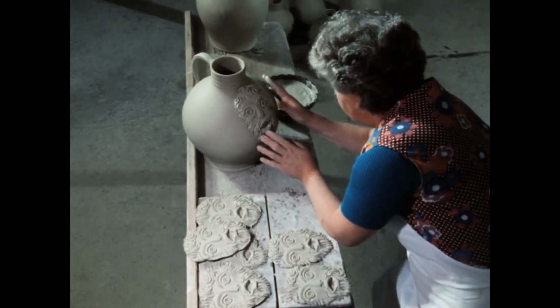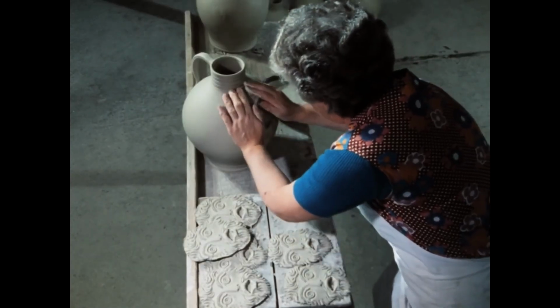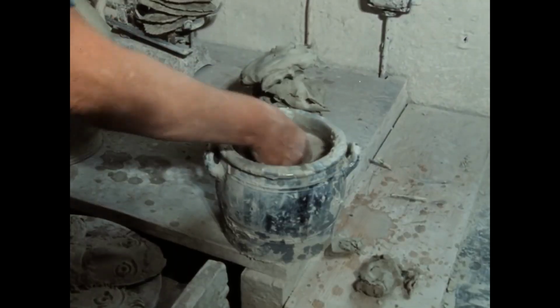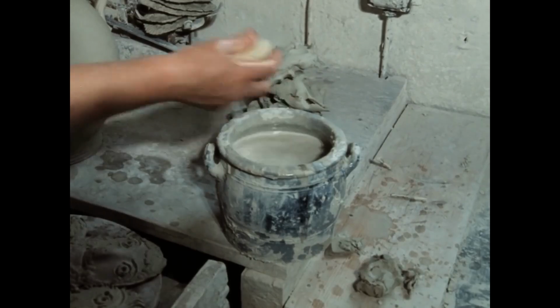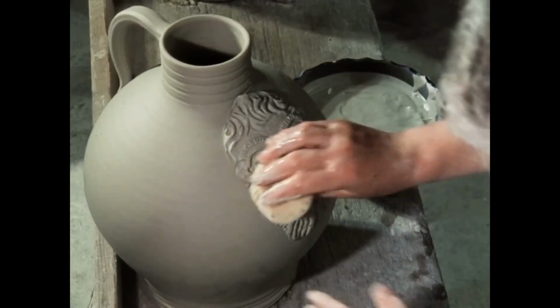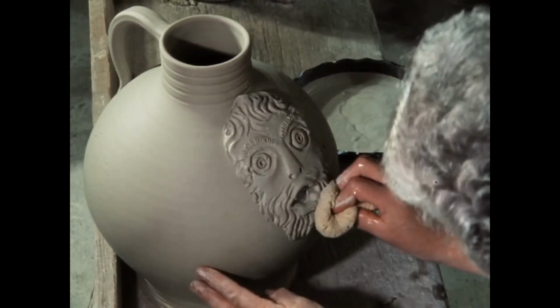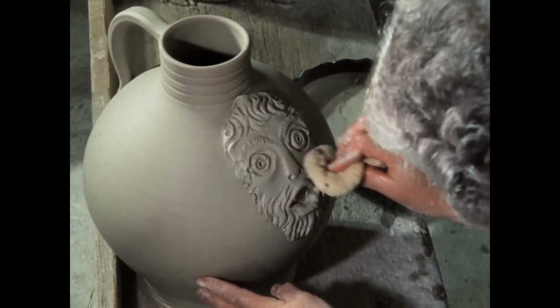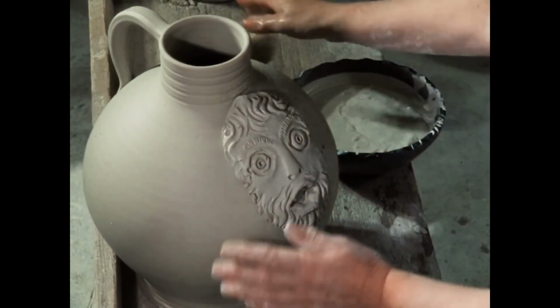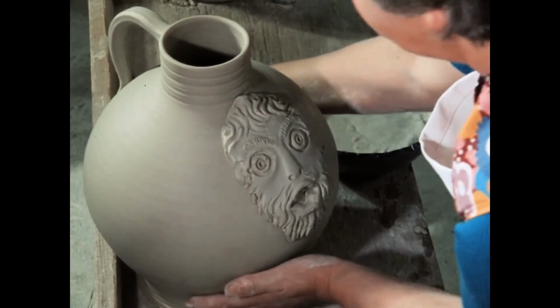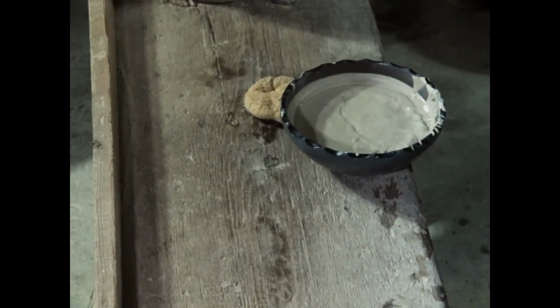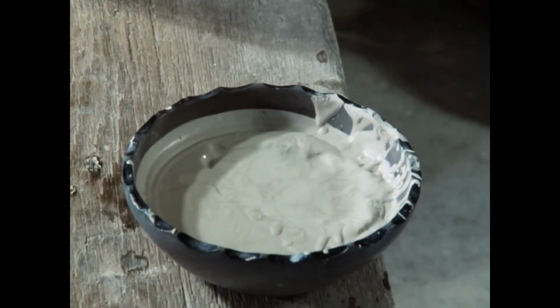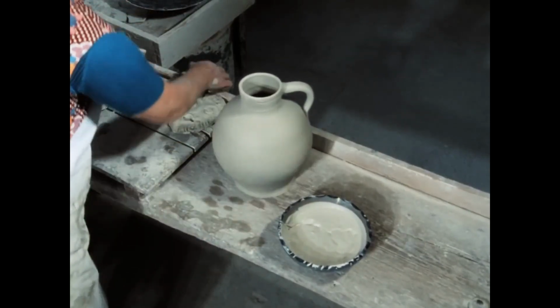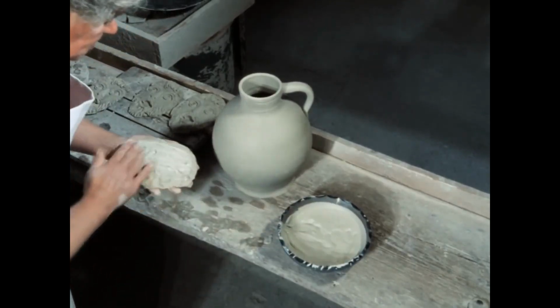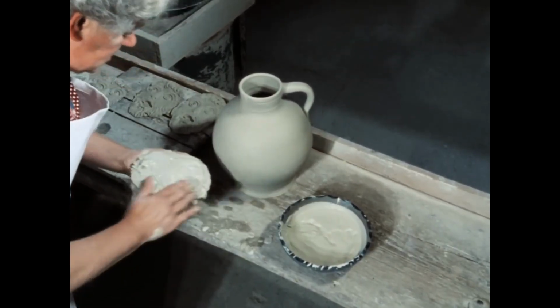At peak heat, the salt goes in. Coarse sodium chloride shoveled directly into the white-hot chamber. The chemical reaction is immediate. Vapors explode outward from the opening. This is how the glaze forms. Not brushed on, not dipped, thrown into fire and chemically grown onto the surface of every vessel inside. Frau Wilms polishes the finished face one last time before it goes on the shelf.